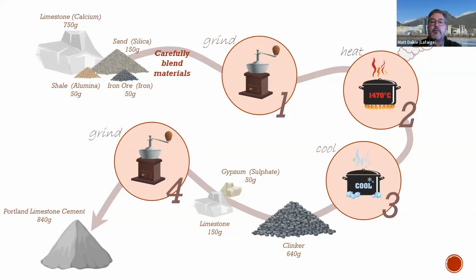We're also using a lot of heat and fuel to actually heat everything up to those temperatures as well. So we're releasing CO2 through the combustion of those fuels. We rapidly cool it down in step 3, and we get clinker at that point. Starting off with 1 kilo of material in the top left-hand corner, we end up with 640 grams of clinker. So that weight difference is all of the CO2 that's been driven off. We mix that with gypsum and limestone, grind it up into a fine powder again, and at that point we get Portland cement or Portland limestone cement.